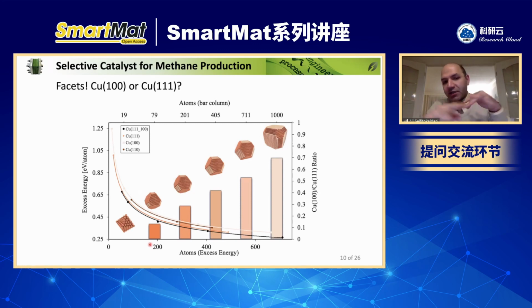First of all, we are running similar DFT computations, a kind of high throughput DFT computation, because the number of computations is a lot, more than a couple of thousand computations, although simple. We started working with silver and tin because copper is for hydrocarbons, multi-carbon products, silver represents catalyst for CO, and tin represents catalyst for formate. So we try to cover all of them. We are running the similar computation for these pure metals, and then the next step is creating the alloy. Hopefully in the near future we can get the answer to see what happens if you have an alloy.